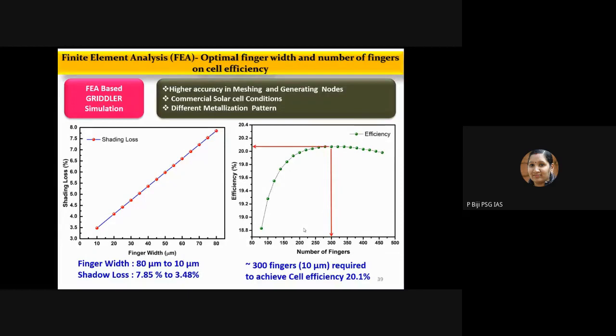This Gridler simulation gives you higher accuracy in meshing and generating nodes. Also, we can use the commercial solar cell conditions during these simulations. Different metallization patterns can also be adopted. Initially we tried to do the optimization of the finger width. As you see in this figure, almost 10 to 80 micrometer different finger widths we have optimized and found out their shading loss in terms of percentage. We found that it varied from almost 7.85 to 3.48 percent as you go down the finger width.